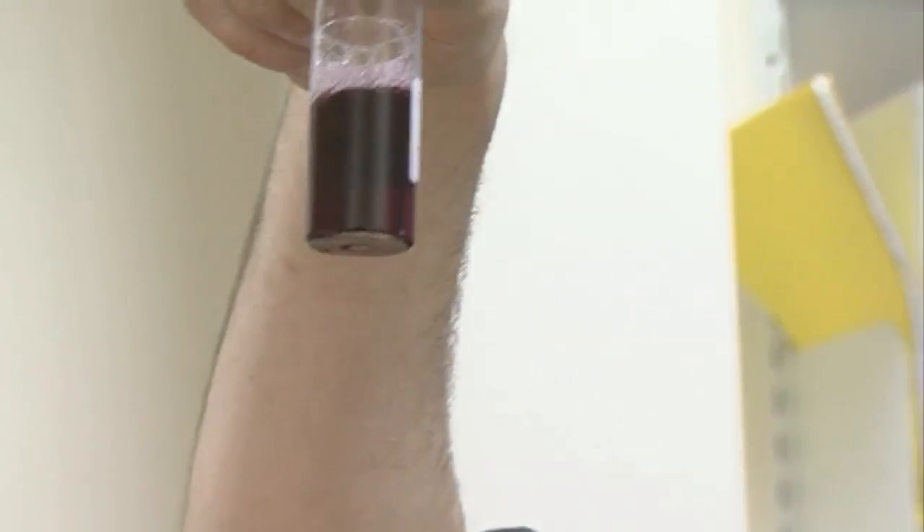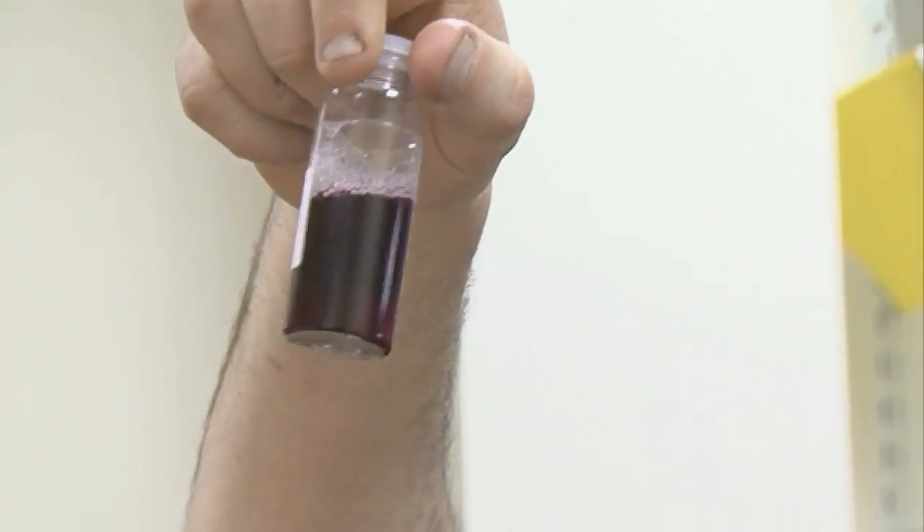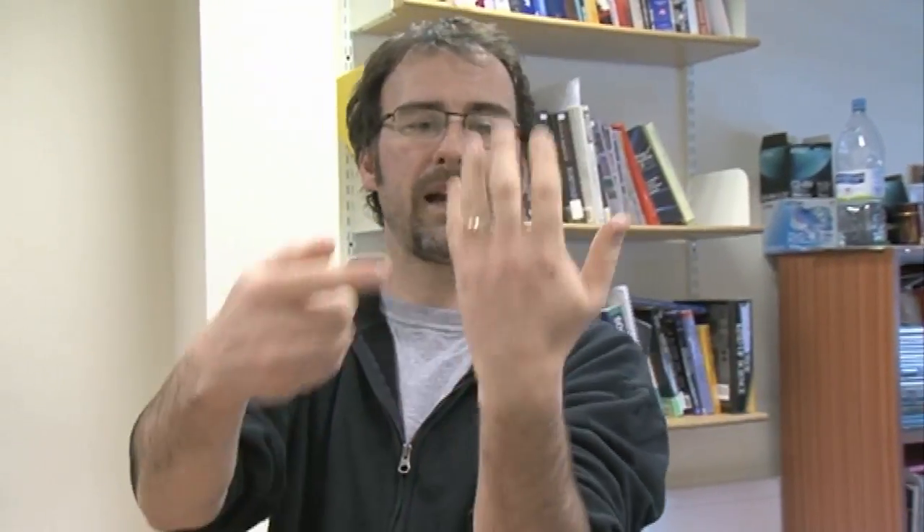is that what you have here are these small chunks of gold, and you keep them separated. Because if you just put neutral gold in there, what will happen is it will all clump back together and you'll end up with something that looks like this. So what you do is, during the chemical synthesis, you actually put a charge on the particles and that keeps them apart.